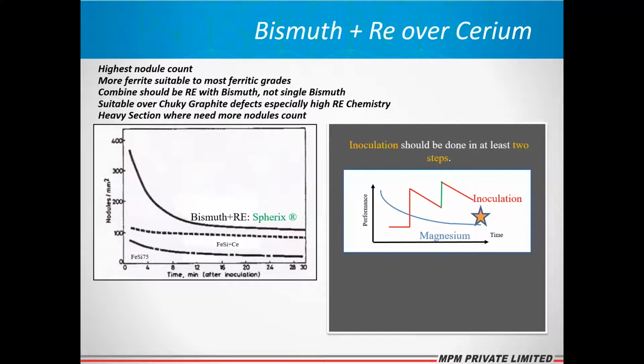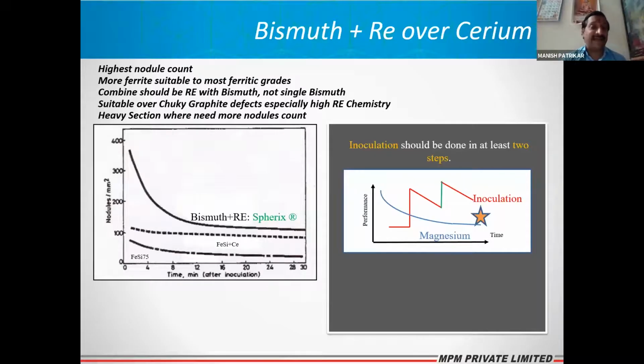So bismuth and RE over cerium. There is again a myth in India that bismuth inoculants promote an elemental effect and a cumulative effect in the casting as a residual element, and later when it builds up in the return scrap, it gives the defect. No. If you are using direct bismuth as a metal, then there are chances of bismuth building up in the return scrap or the casting. Direct bismuth is a poison for metal. But when you are using bismuth in combination with RE, then it acts like a poison curer and gives you a better effect in terms of all elements.